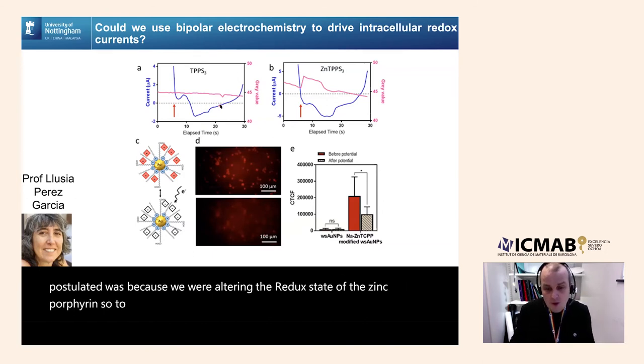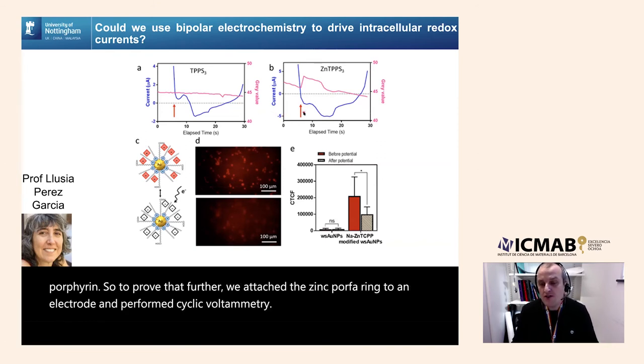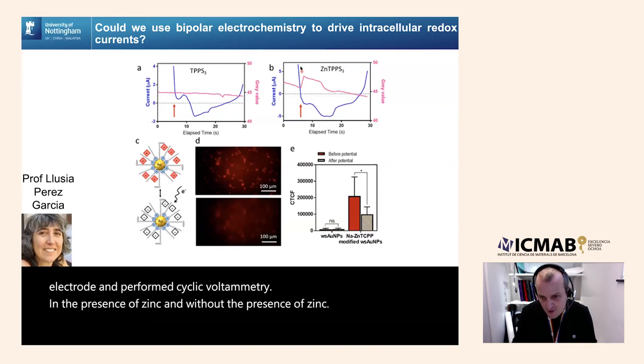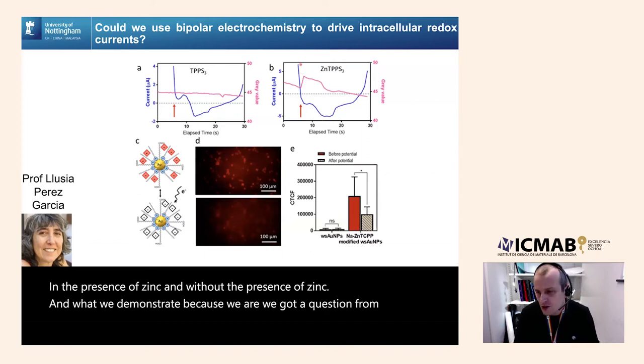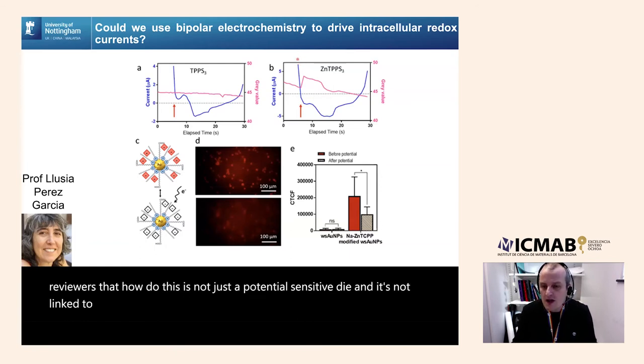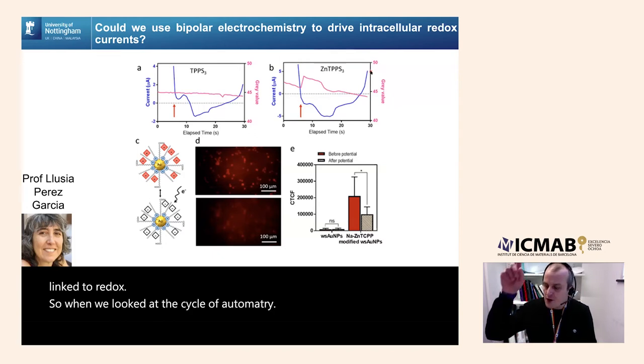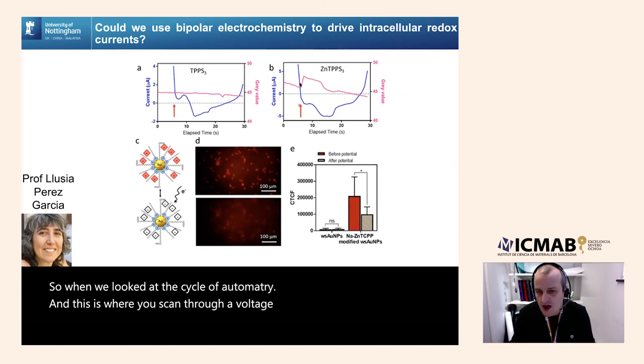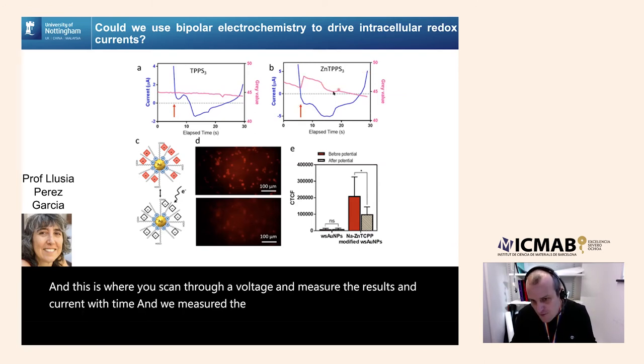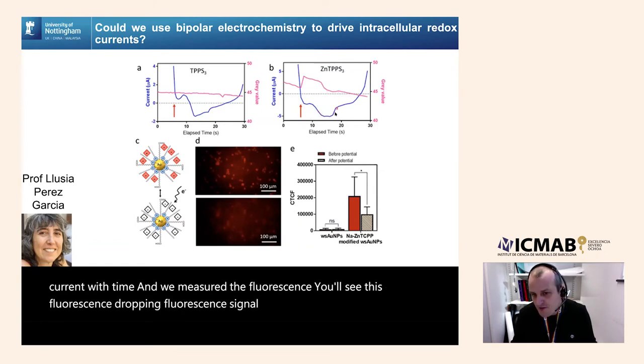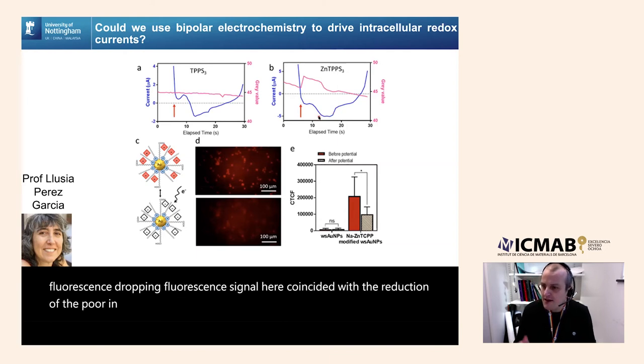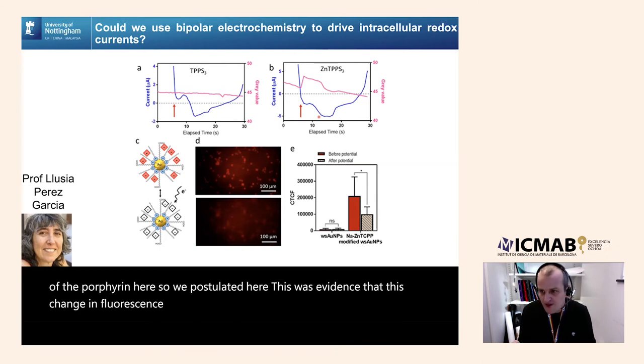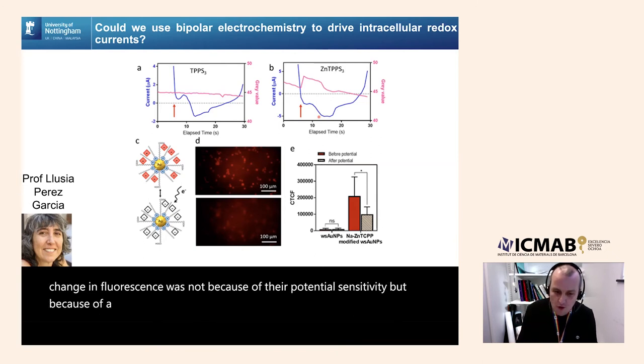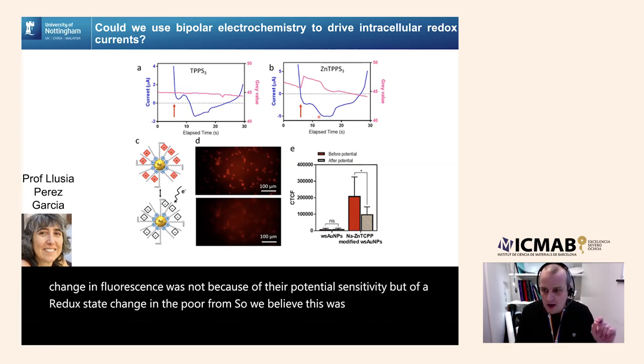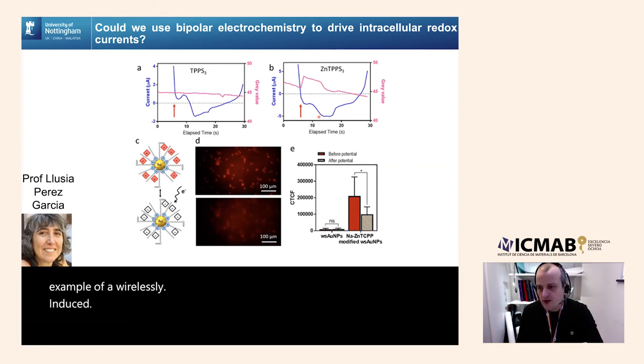So to prove that further, we attached the zinc porphyrin to an electrode and performed cyclic voltammetry in the presence of zinc and without the presence of zinc. We got a question from the reviewers: how do you know this is not just a potential sensitive dye and it's not linked to redox? So when we looked at the cyclic voltammetry, where you scan through a voltage and measure the resulting current with time, and we measured the fluorescence, you'll see this dropping fluorescence signal here coincided with the reduction of the porphyrin here. So we postulated this was evidence that this change in fluorescence was not because of a potential sensitivity, but because of a redox state change in the porphyrin. So we believe this was the first example of a wirelessly induced redox state change inside the cell.